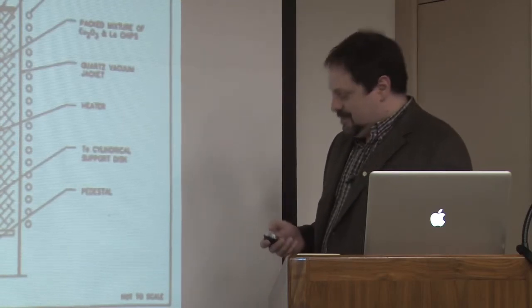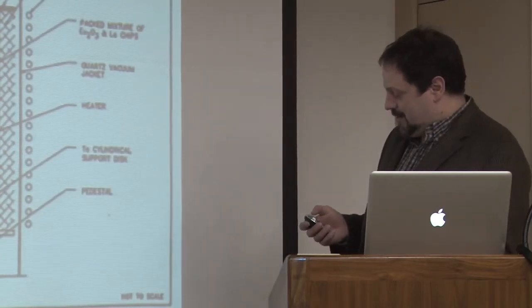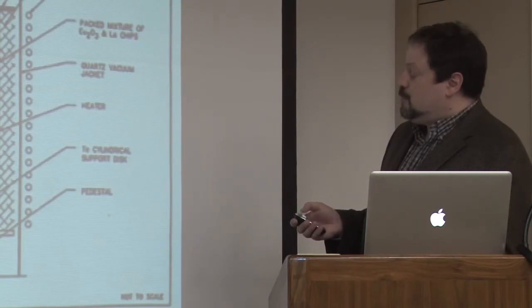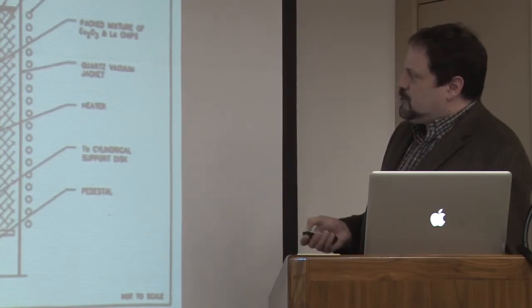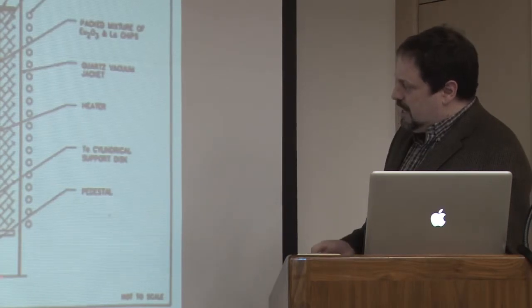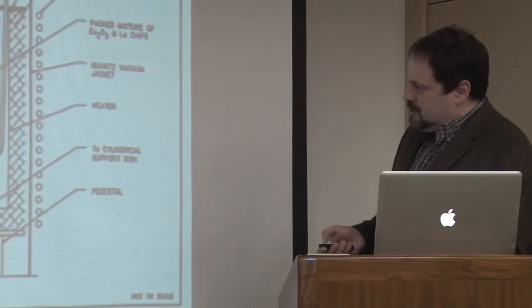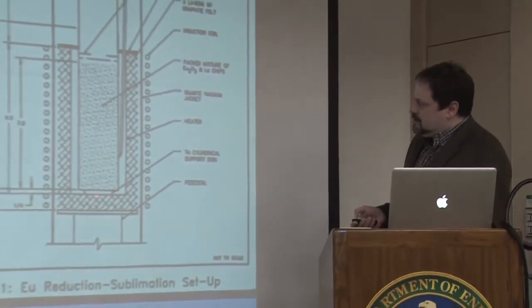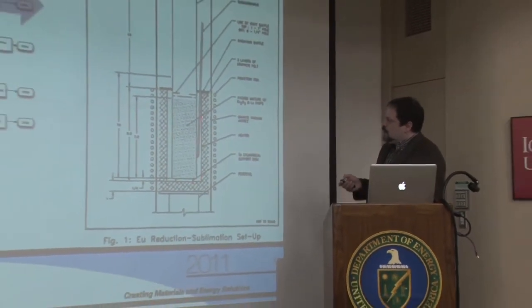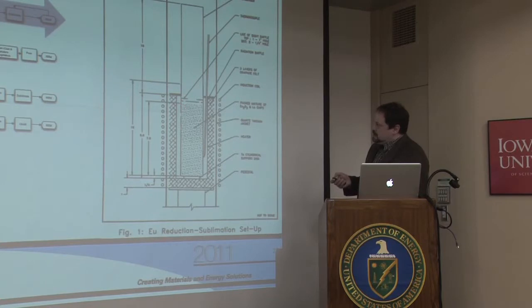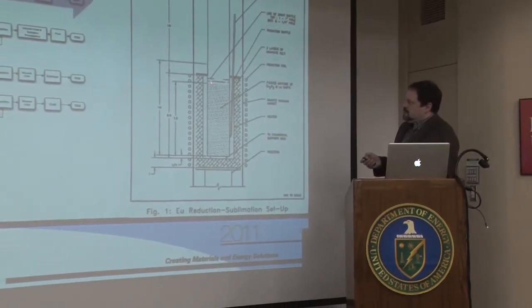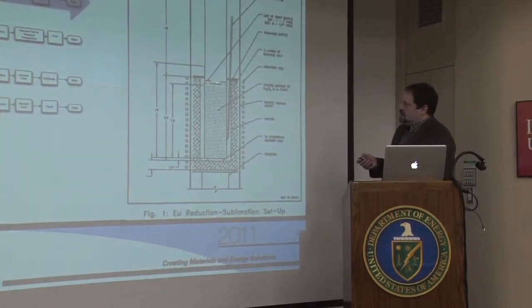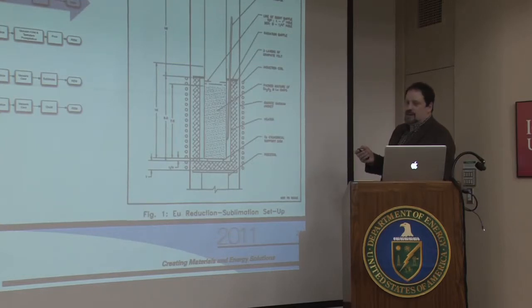This finely detailed image, which is kind of hard to see from where you're at with this bad projector, shows our setup. This is a quartz containment for our vacuum. This hatching is graphite insulation on a tantalum boiler or heater can, as we call it. This is what we call the boiler can, or reduction vessel, also made of tantalum, and here's the mixture. Heat it up, the metal gas comes up through the baffle and collects somewhere on the inside of this condenser can.